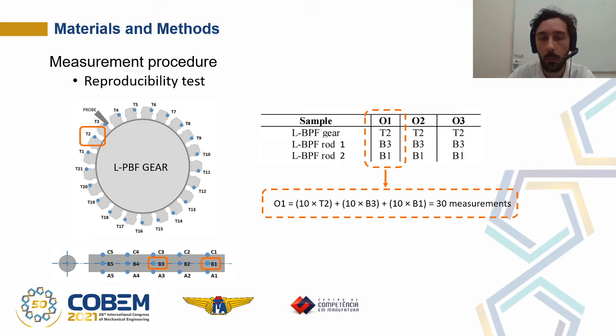And to achieve this goal, it was defined that each operator would perform 10 measurements on each sample in identical predetermined regions. 10 measurements were performed in region T2 in the laser powder bed fusion gear, 10 measurements in region B3 in the rod as built, and 10 more measurements in region B1 in the other rod, stress relief, totaling 30 measurements for each operator.